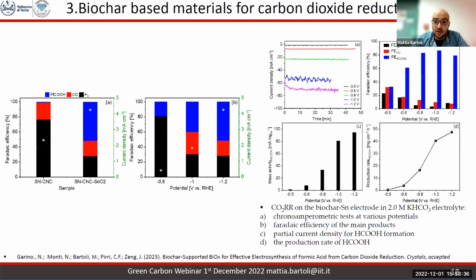These particles were used also for the same reaction that you saw before, conversion of CO2, matching the same results that we obtained by using bismuth. But in this case, we use tin. It's far and considerably more expensive.